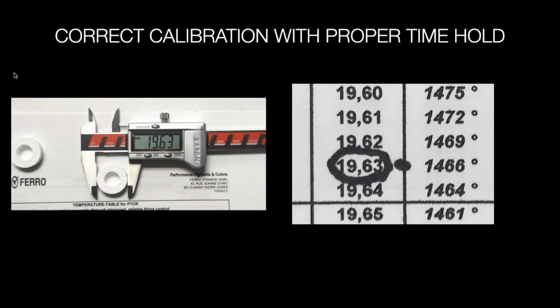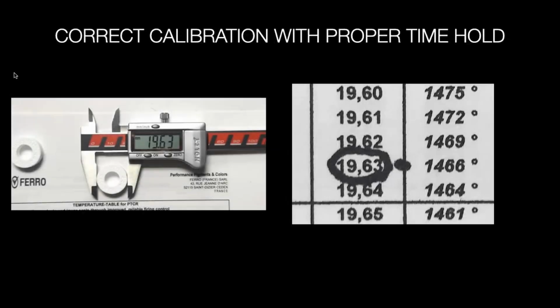And again, what do you do on the bigger cases? So I know the furnace is at the right temperature, and how long you leave the zirconia in there is irrelevant because the rings are not going to be in there. So we know that we're holding it at 1450 for X number of hours, and that's what the zirconia needs to change to a sintered body. So let's look at the furnaces.